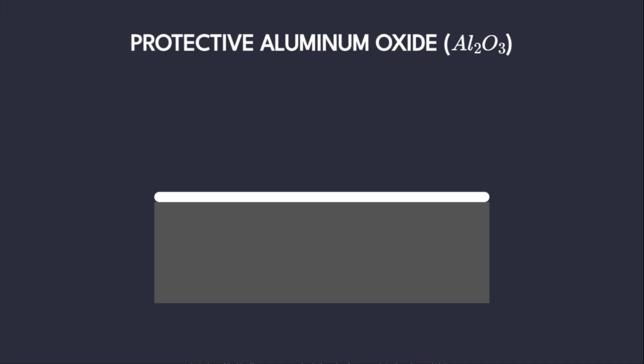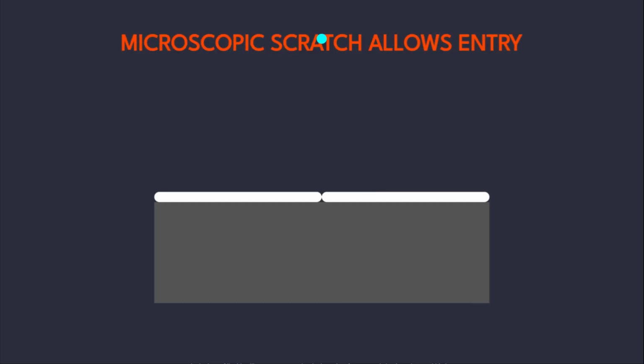Aluminum is naturally protected by a transparent, highly stable layer of aluminum oxide, also known as alumina. This ceramic layer is what prevents aluminum from reacting instantly with oxygen and water in the atmosphere. To destroy the aluminum, gallium must first bypass this protective skin. If the oxide layer is perfectly intact, gallium may sit harmlessly on the surface. However, any microscopic scratch, thermal stress, or mechanical deformation provides an entry point. Once the gallium makes contact with the raw aluminum metal beneath the oxide, it begins to spread laterally.